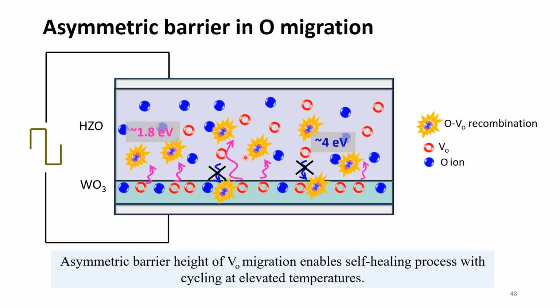Staying in HZO, what do the oxygens do? It recombines with the vacancies that are generated in HZO with cycling at elevated temperature, partially heals those vacancies, delays the breakdown, for which we are getting higher endurance in the devices with tungsten oxide layer. And this is the reason why we are calling them self-healing capacitors.